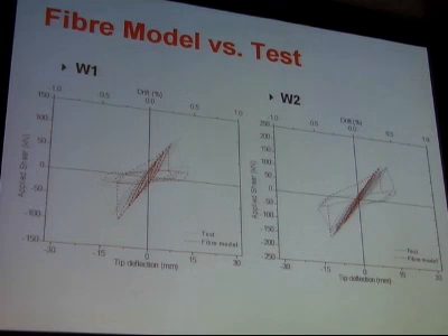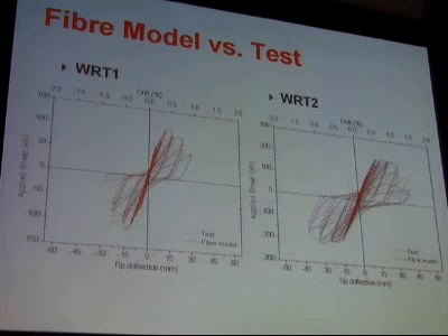And we developed the fiber models to predict the response of the walls. Here we can see the fiber model versus the test, which is in the light shaded area there. It's difficult to get a really good, accurate fiber model for the case where it's extremely brittle, but it was fairly close. For the CFRP retrofit, the wrap solution, here's our fiber model in red, and the light gray is